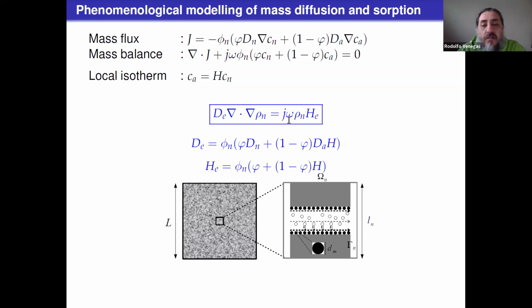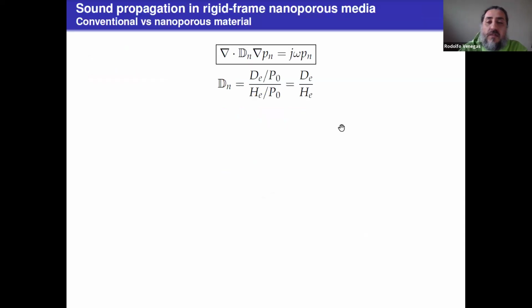So this is interesting because it helps us to compare a conventional material with a nanoporous material. And if we write this equation in terms of pressure by assuming that the process is isothermal, we can identify this pressure diffusivity just like the ratio between the effective diffusion coefficient and this effective absorption coefficient, which works in pretty much the same way as a porosity, but an effective one that can take values larger than 1, and we will see the effect later.